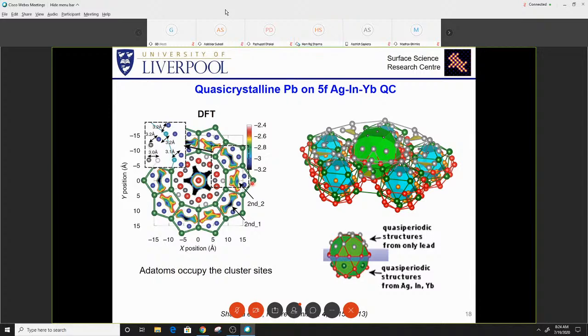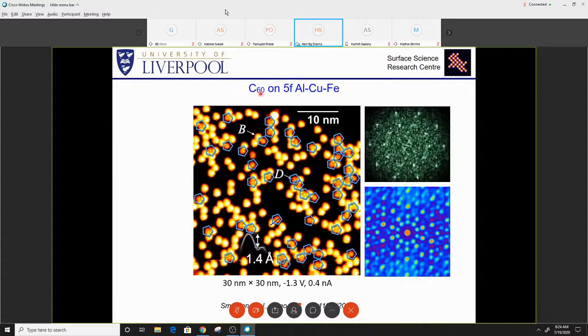So here are some examples of molecules. For example, we deposit C60 on various quasicrystals. One example: these protrusions here, dots, correspond to single C60 molecules. Here you can see two different types of molecules, darker molecules and lighter molecules. The darker molecules are located at the center. You see many pentagons. Again, if you deposit more C60 molecules, it goes layer by layer and you can map the structure. As usual, we use Fourier transform and also confirm the C60 molecules.